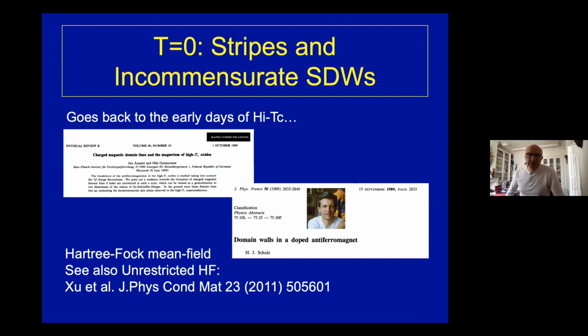But basically what I would like to tell you in the few minutes that remain is how do we actually reconcile that with the very large body of evidence that documents the existence of stripes and incommensurate spin density waves at low temperature or zero temperature in the weakly doped Hubbard model. So that goes back to the early days of Hi-Tc. Even static mean field of the Hartree type has, and that's how they were theoretically discovered, stripe formation. These are two very beautiful papers that demonstrate that.